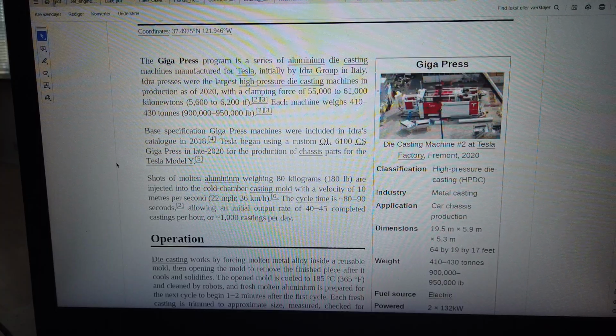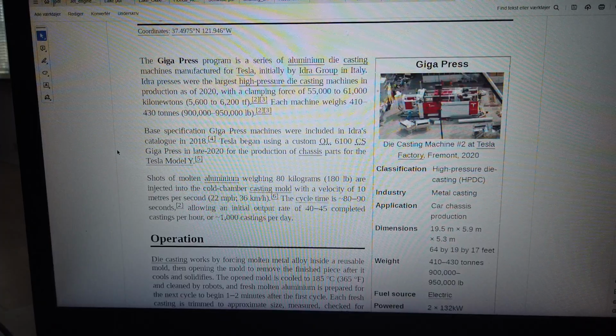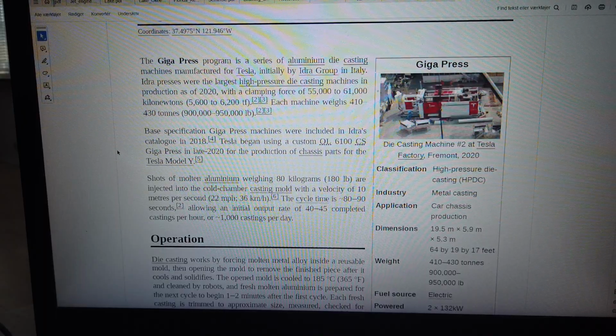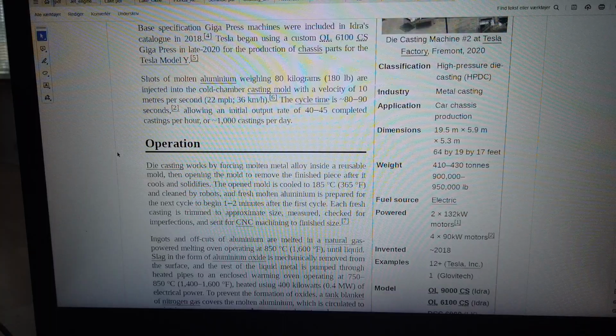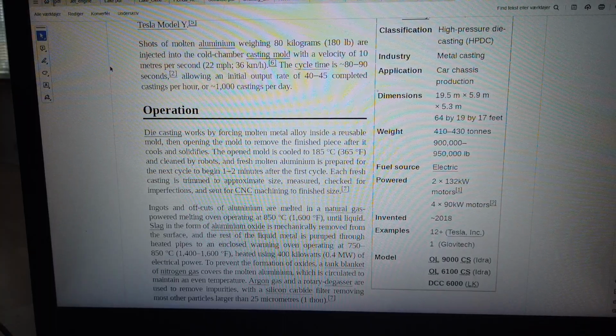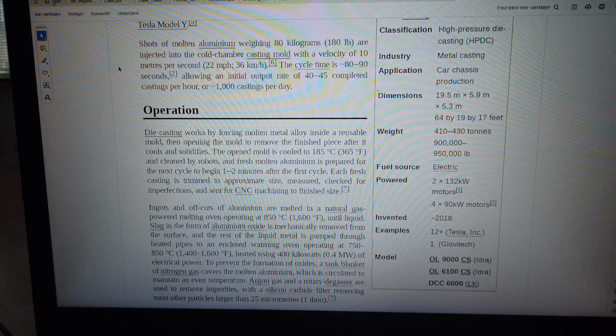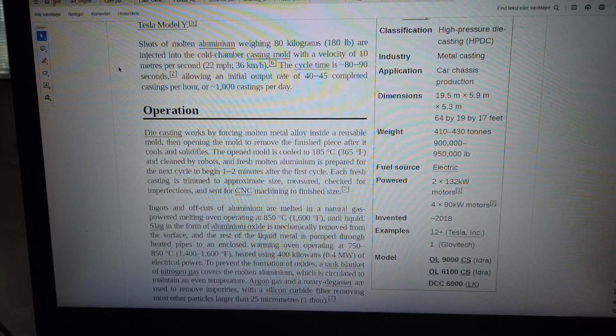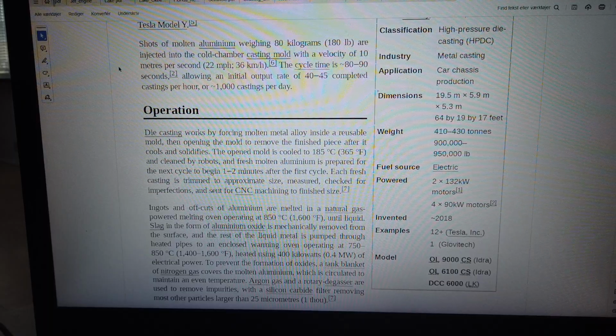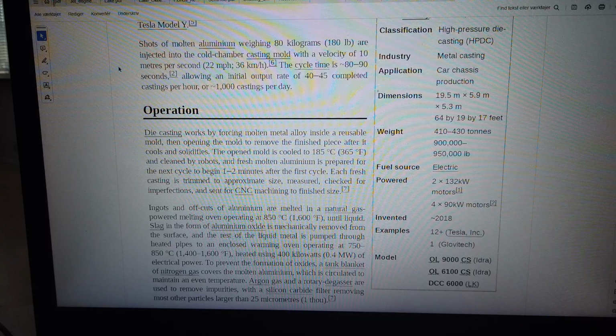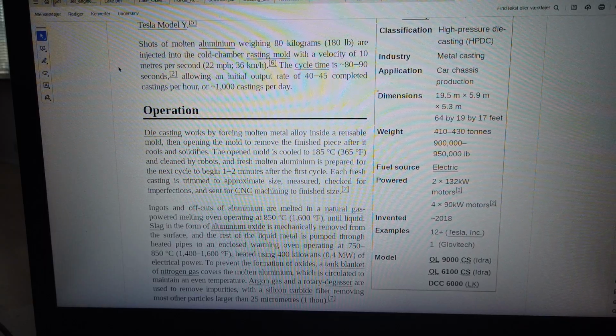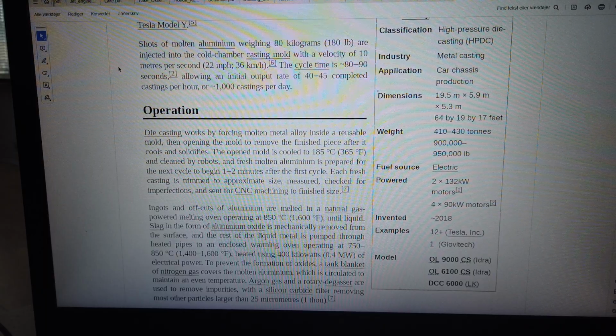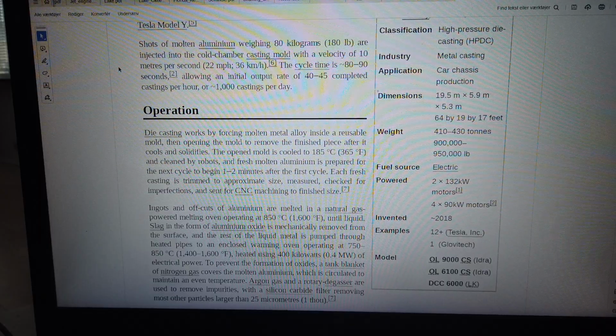Tesla began using a custom OL6100 CS Giga press in late 2020 for the production of chassis parts for the Tesla Model Y. Shots of molten aluminium weighing 80 kilograms, 180 pounds, are injected into the cold chamber casting mold with a velocity of 10 meters per second, 22 miles per hour, 36 kilometers per hour. The cycle time is 80 to 90 seconds, allowing an initial output rate of 40 to 45 completed castings per hour, or 1,000 castings per day.